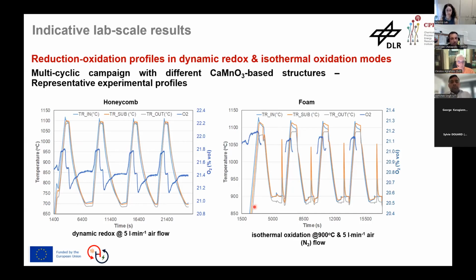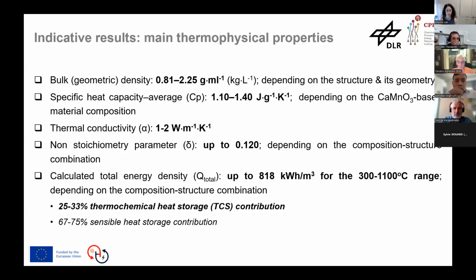As shown, oxidation leads to a rapid increase in the substrate temperature and the downstream gas temperature due to exothermic reactions. The upstream temperature, you cannot really see it here, but remains unchanged as it is unaffected by the reaction zone. These experiments help us compare the performance of different materials, structures, and geometries. So let's now look at some indicative results.